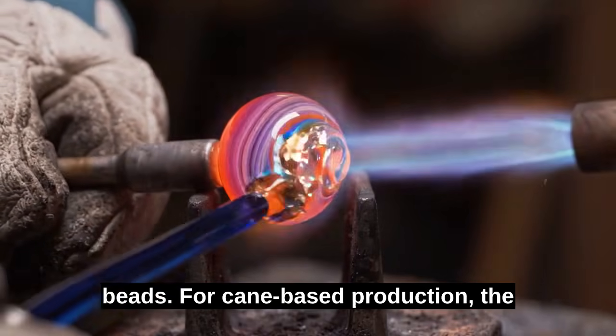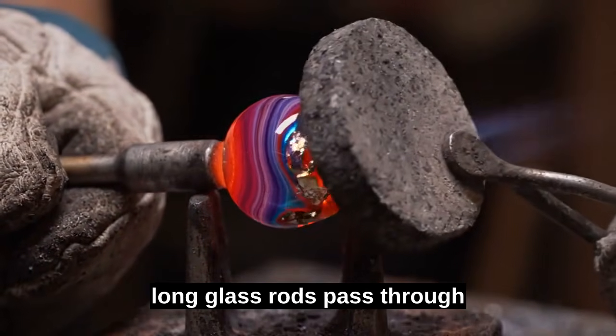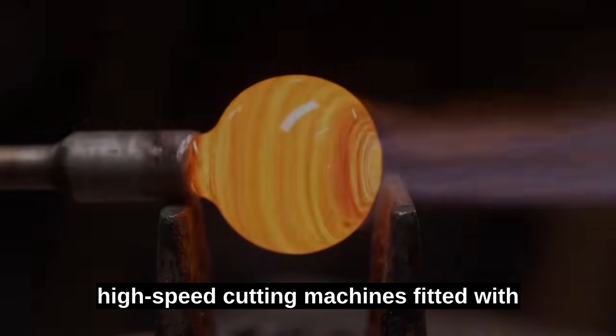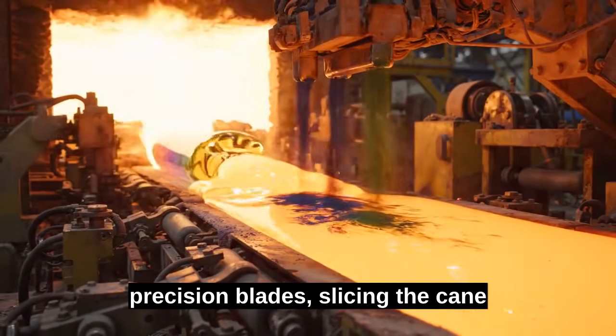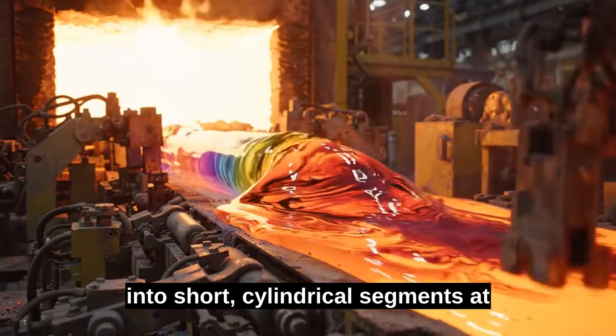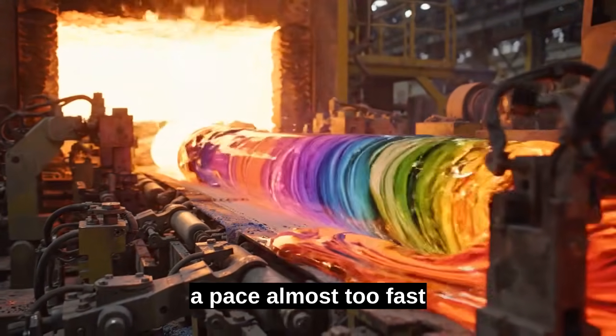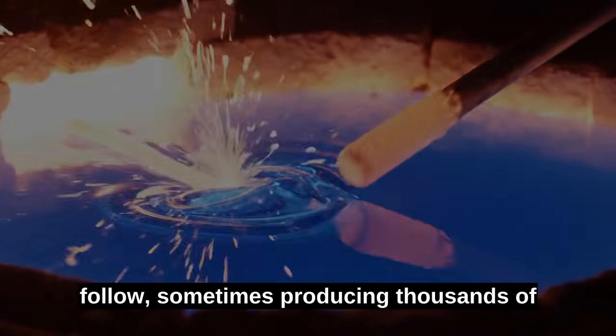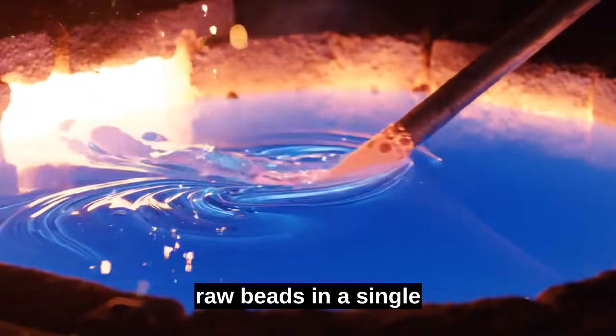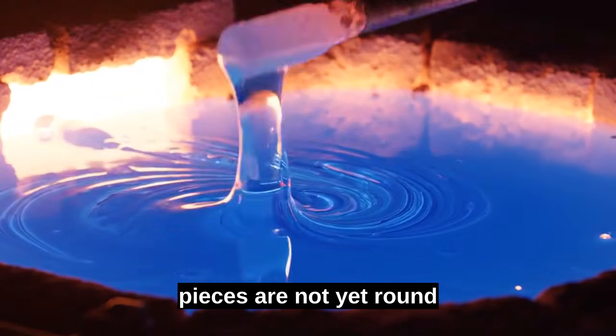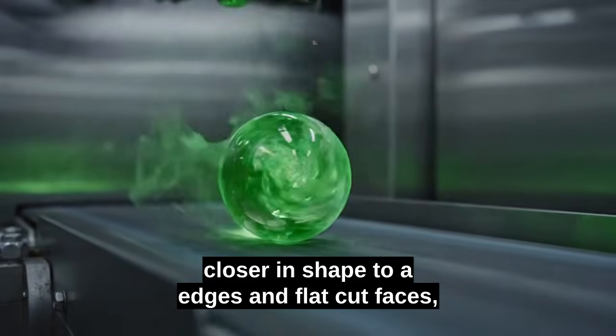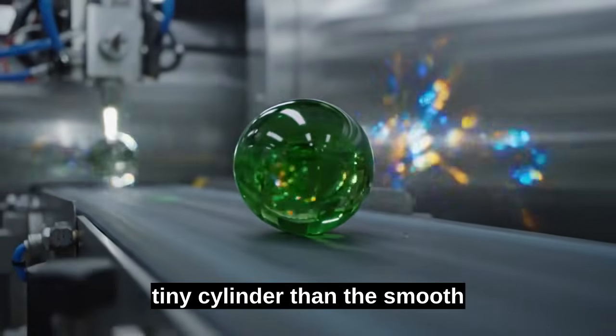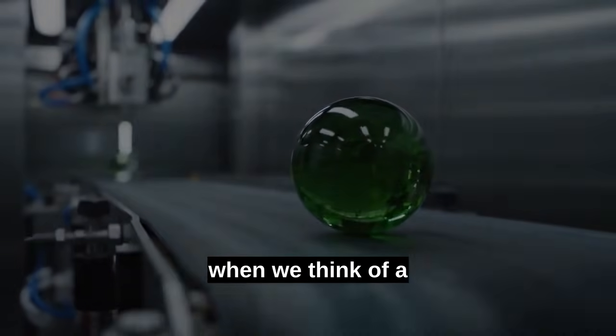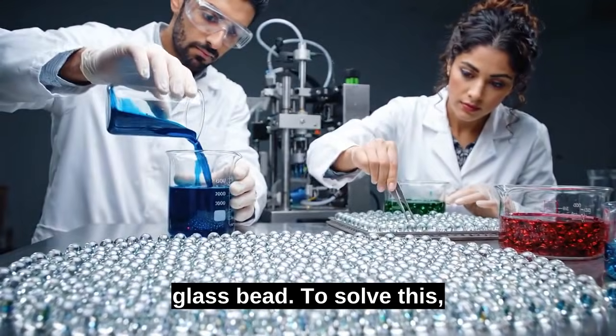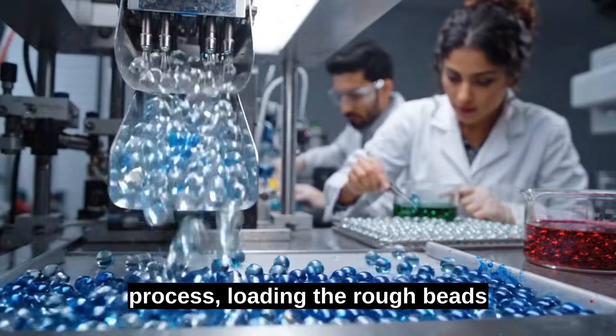it faces its next transformation, being cut down into individual beads. For cane-based production, the long glass rods pass through high-speed cutting machines fitted with precision blades, slicing the cane into short, cylindrical segments at a pace almost too fast for the human eye to follow, sometimes producing thousands of raw beads in a single minute. These freshly cut pieces are not yet round, though. Many still carry sharp edges and flat-cut faces, closer in shape to a tiny cylinder than the smooth sphere most of us picture when we think of a glass bead.